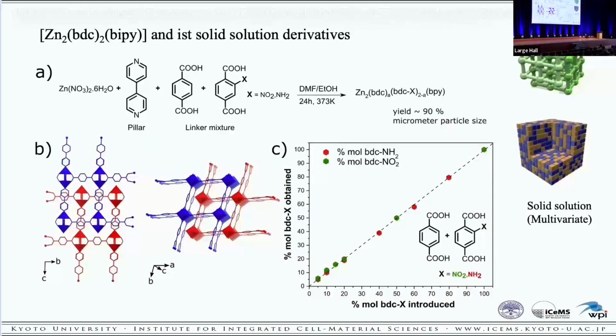To meet this objective, we synthesize an interpenetrating framework using zinc, 4,4'-bipyridine, and benzene dicarboxylate. Here, BDC has a substituent such as amino or nitro groups. Here we adopted the solid solution method of mixing different ligands. This is a so-called multivariate MOF.